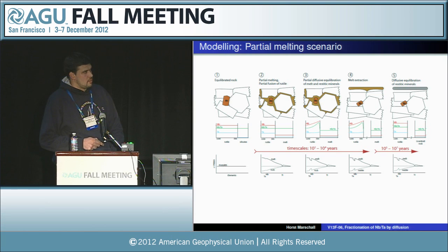So we have this simple sketch here. This is a rock with a rutile crystal. You generate partial melt. Some of the rutile will dissolve into the melt until the melt is saturated in titanium. And then this is the sketch showing niobium and tantalum profiles through the rutile and through the neighboring rock. And then as the rutile has dissolved, it has oversaturated the melt in niobium and tantalum. It's like if you dissolve a garnet crystal and you get an oversaturation in manganese in the surrounding rock. And this will simply lead to a back diffusion of the highly compatible elements into the restitic rutile. And depending on your timescales, this will be a very long profile or very short profile, but at some point the melt will be extracted, leaving the rutile partially equilibrated, depending on timescale.